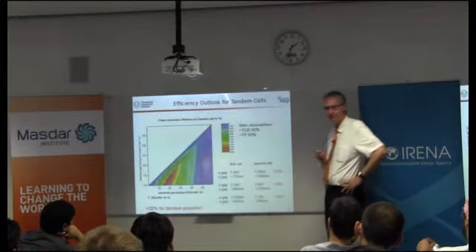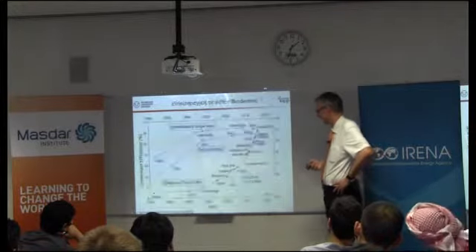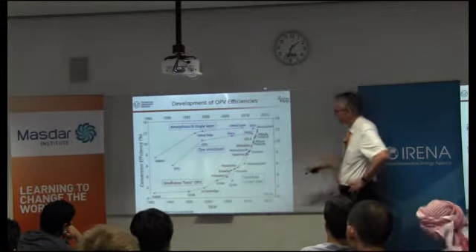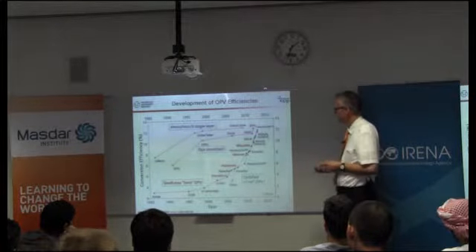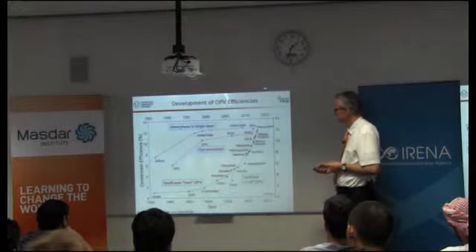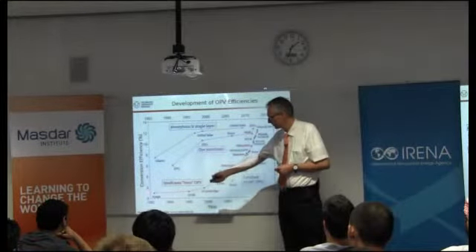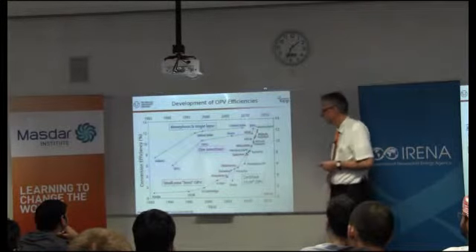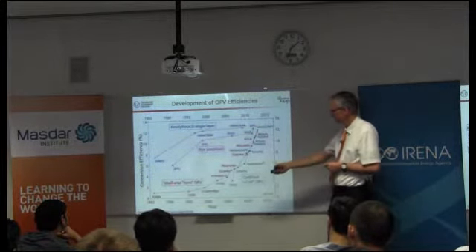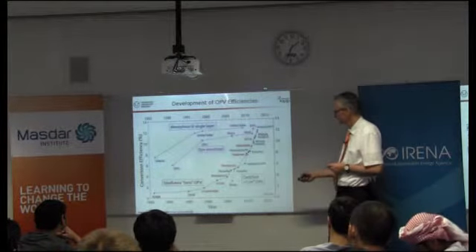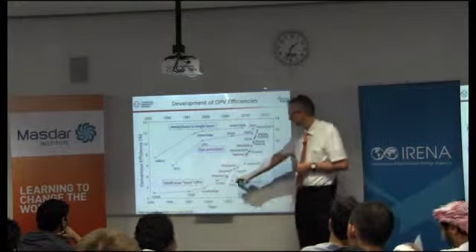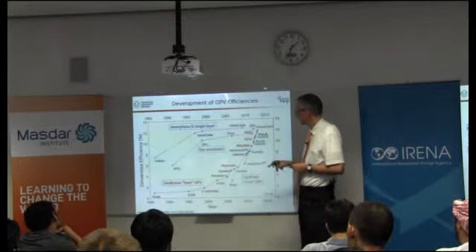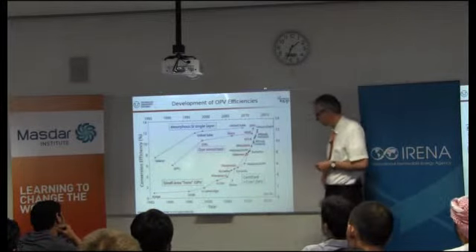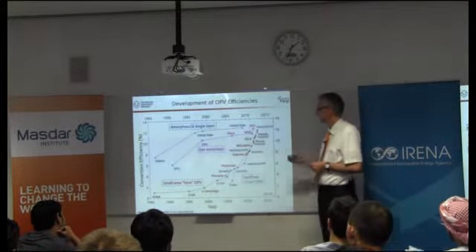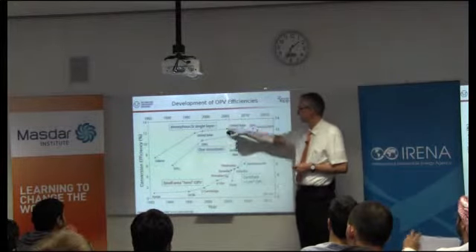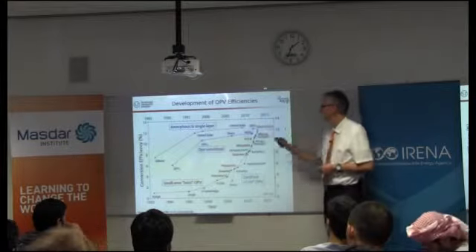Silicon has been a very difficult contender in PV to beat, and it will stay like that. This is now the enlarged graph of this NREL plot, showing the lower right corner. And the main message is that organic PV started with work at Kodak, Tang in 86. For a long time there were only small area cells, but in the last few years, we've also seen larger area certified cells. And as you can see, the development has been enormous, and Heliatek, which is in conjunction with my home institute, the world record holder, is now at 12%, which is approximately equal with the dye-sensitized cell and the amorphous single layer. So they are all on the same level.